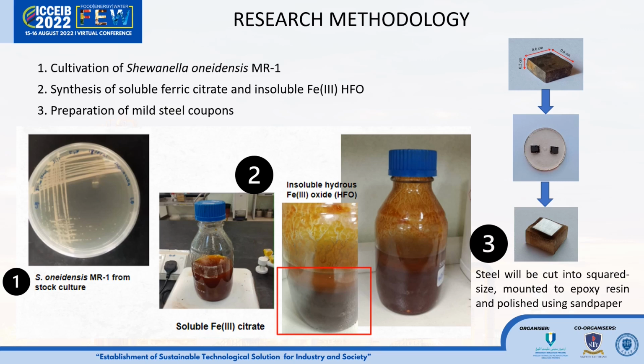In the second stage, we synthesized both soluble ferric citrate and insoluble hydrous ferric oxide, HFO, via precipitation technique using NaOH, sodium hydroxide. In this study, either soluble ferric citrate or insoluble HFO would be the electron acceptor for Shewanella oneidensis MR-1. In the third stage, steel was cut into square size, mounted in epoxy resin, and polished using sandpaper until a mirror surface was obtained.